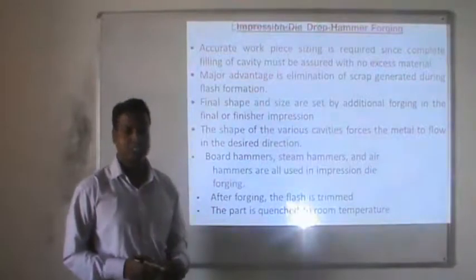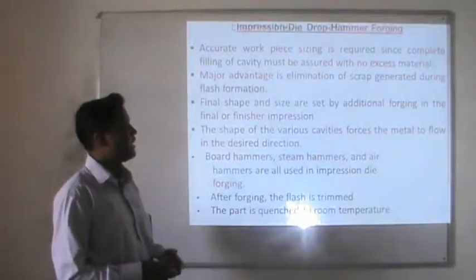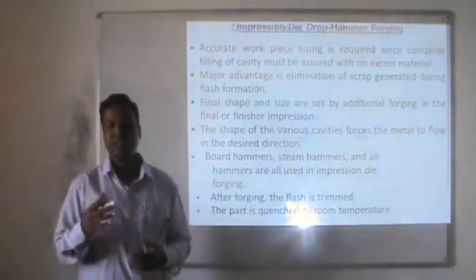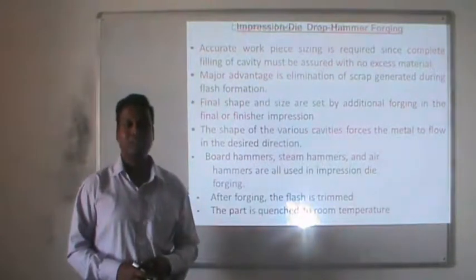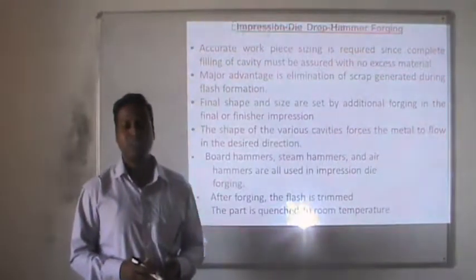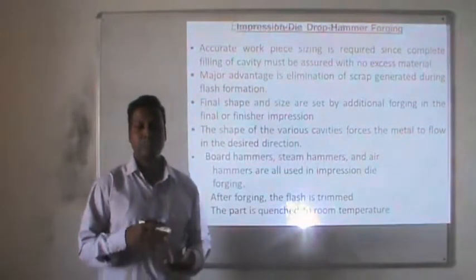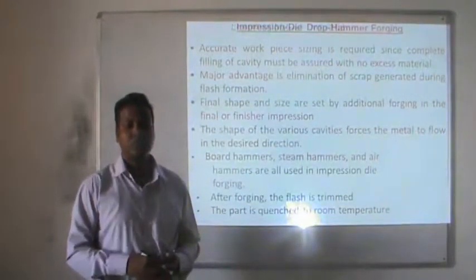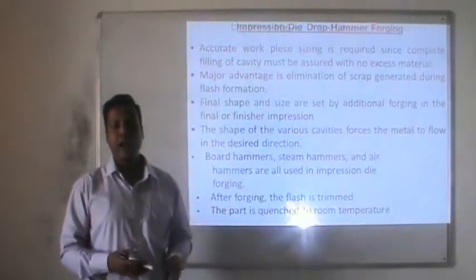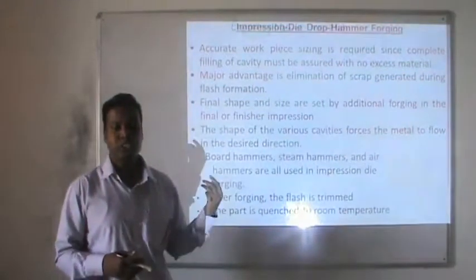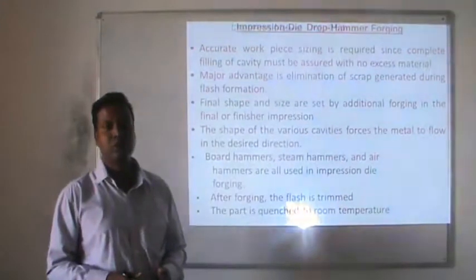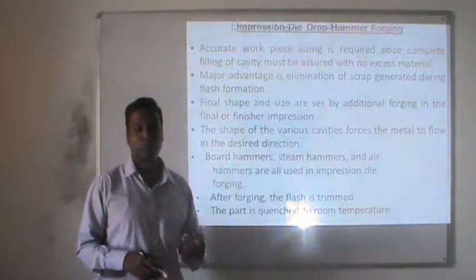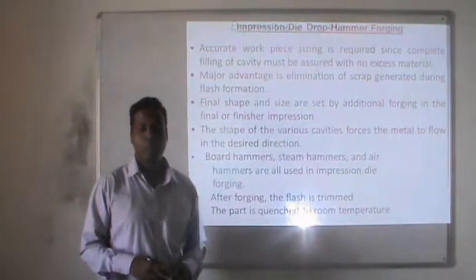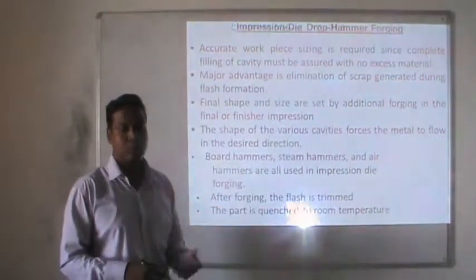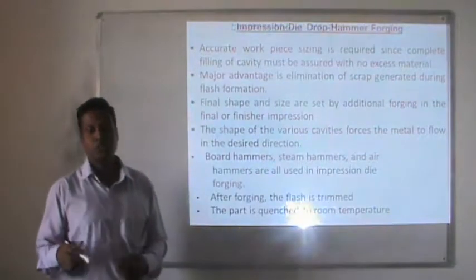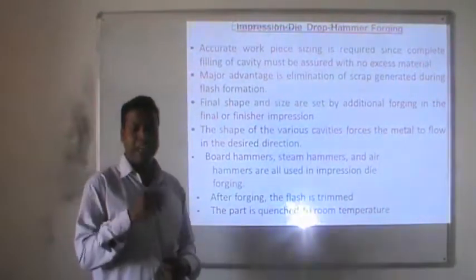Impression die drop hammer forging. Again, accurate workpiece size is required, since complete filling of the cavities must be assured with no excessive material. The major advantage is the elimination of the scrap generated during flash formation. The final shape and size are set by additional forging in the final or finisher impression. The shapes of the various cavities force the metal to flow in the desired direction. Board hammers, steam hammers and air hammers are used for impression die forging. After the forging, the flash is trimmed off.